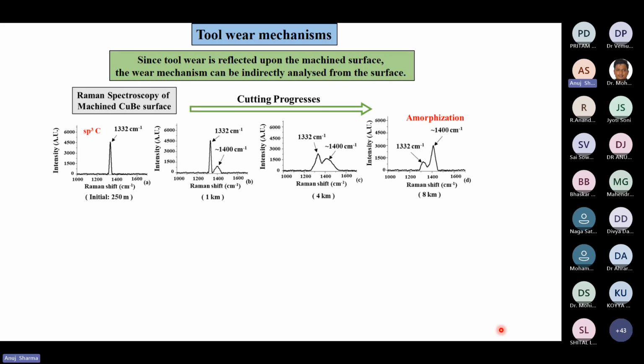So similarly, it was seen when the Raman spectroscopy was carried out on the copper beryllium surface. Basically, when tool wear takes place, the atoms from the tool come onto the workpiece surface. So the surface was also analyzed with Raman spectroscopy, and it was seen that at different cutting distances, there were different peaks observed.